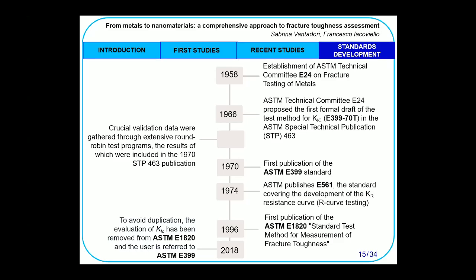Just the year after the Irwin works, in 1958, the ASTM Technical Committee E24 on fracture testing of metals was established. In 1966, we had the E399-70T. T stands for tentative standard. And after extensive round-robin test programs, only after that, we had in 1970 the first publication of the E399 standard. And only after 30 years from the Irwin results, we had the publication of the ASTM E1820 standard. And only 6 years ago, we had the new ASTM E1820 standard, removing the evaluation of K_IC from this standard in order to avoid overlap with the ASTM E399.